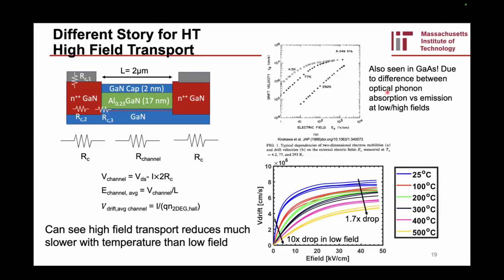And ultimately, this is because of the different phonon scattering mechanisms. In both cases, phonon scattering is what's causing the decrease in the drift velocity. But in the low field case, it's more phonon absorption. The electrons need to basically meet a phonon, absorb a phonon, and scatter across a phonon. And so it depends on the number of phonons, which is very dependent on the temperature. On the other hand, in the high field case, it's more of a phonon emission process. So the electron doesn't have to wait around to see a phonon. It can just emit a phonon directly. And so that has a very weak temperature dependence.